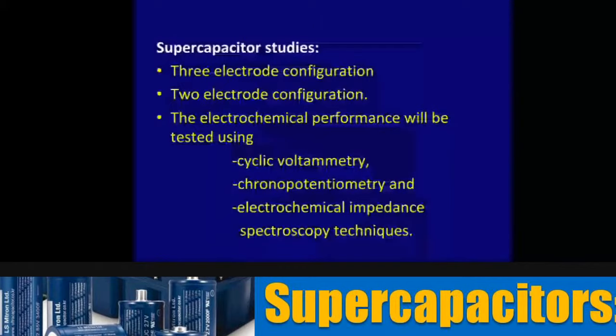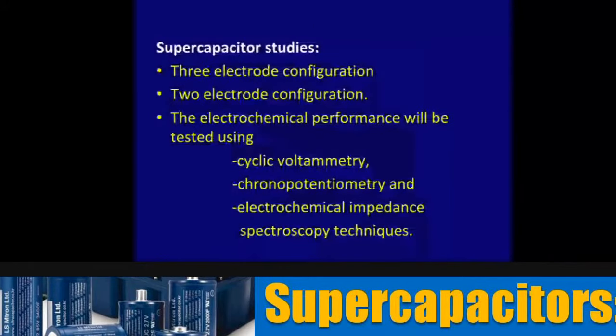And similarly, our interest is to know what is happening with the equivalent series resistance. The ESR has to be measured, and that is measured through electrochemical impedance spectroscopy, where we measure the real and imaginary part of the impedance at different frequencies, and by fitting this data to an equivalent circuit, the series resistance and the capacitance can be evaluated.